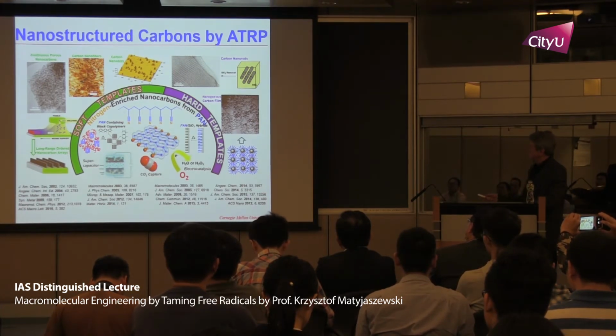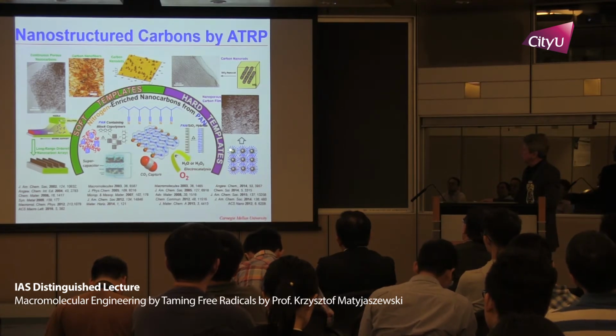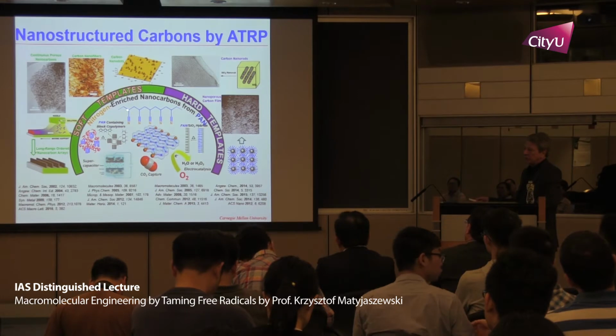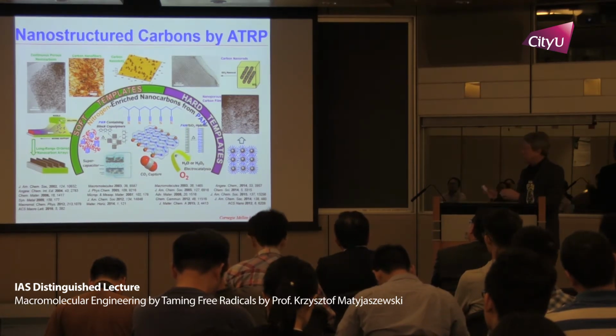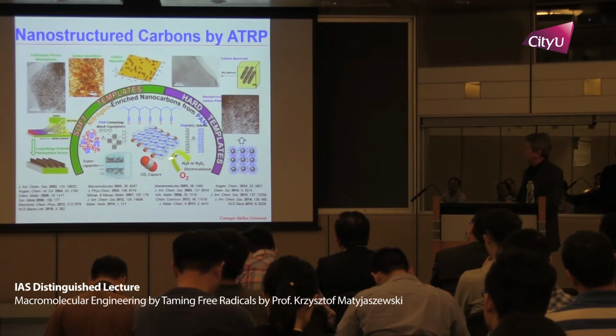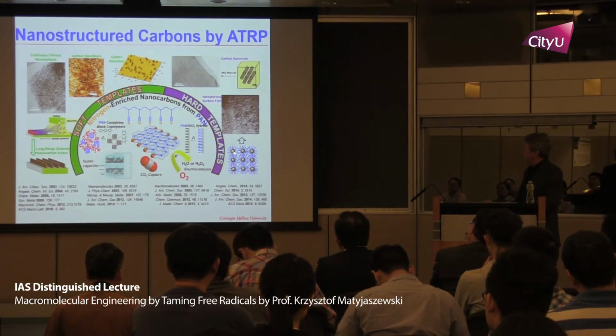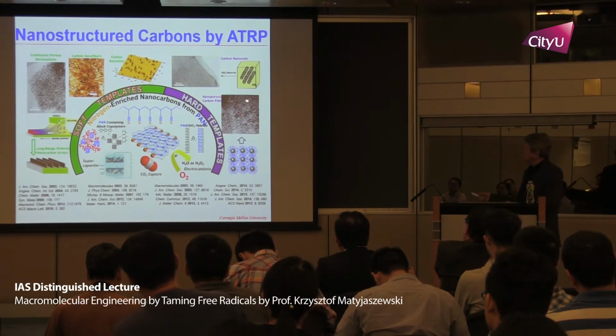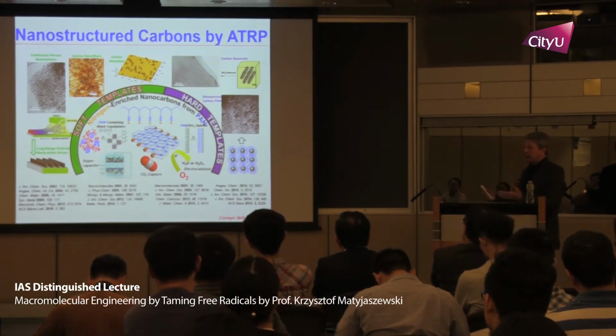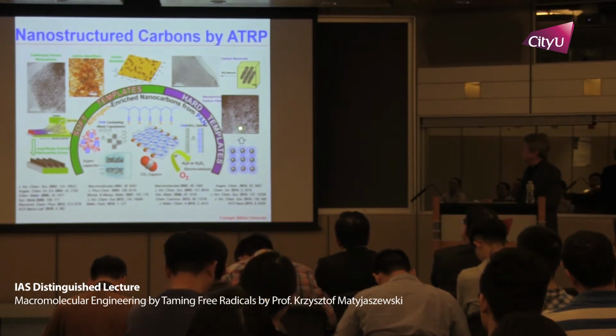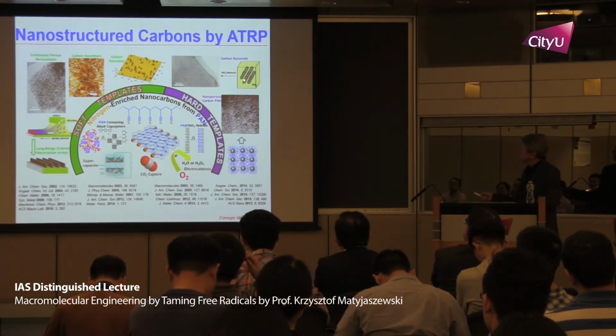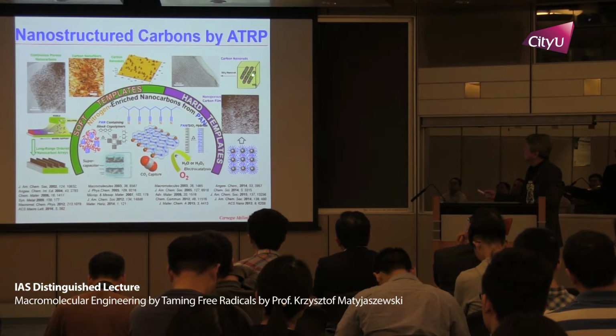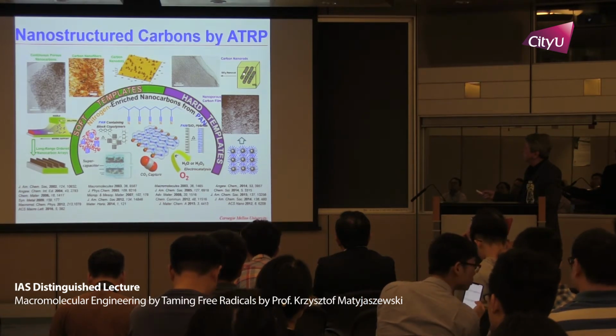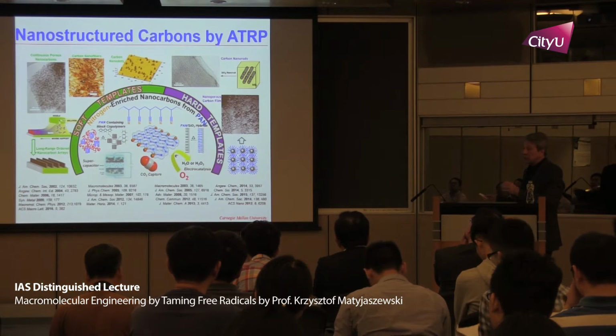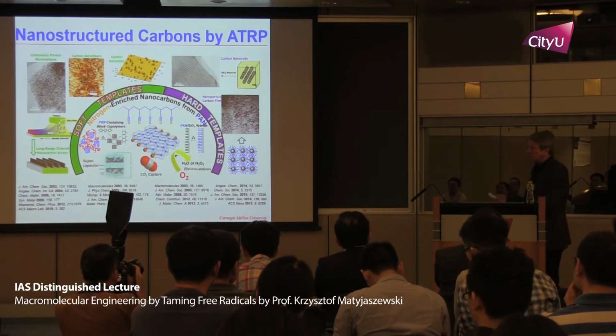So I mentioned to you that we are also interested in nanocarbons or electronic materials in general. So on one side, we start with these nanoparticles, we graft them with polyacrylonitrile, and then we graphitize the system to make graphitic structures. We then etch this silica, and then you have a one-component, highly porous system, with porosity up to 1,000 square meters per gram. I mentioned also that we can use mesoporous silica, 10 nanometers, cylindrical openings, and then you can grow polyacrylonitrile, graphitize, remove silica, and get these 10 nanometer replicas of nitrogen-doped carbons.